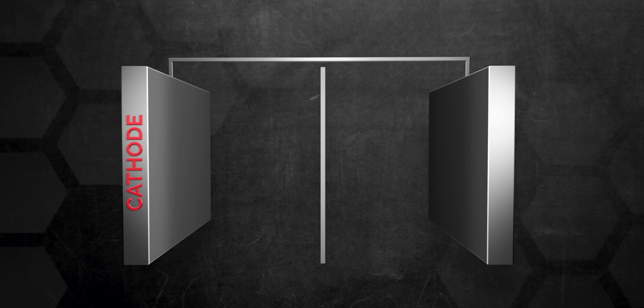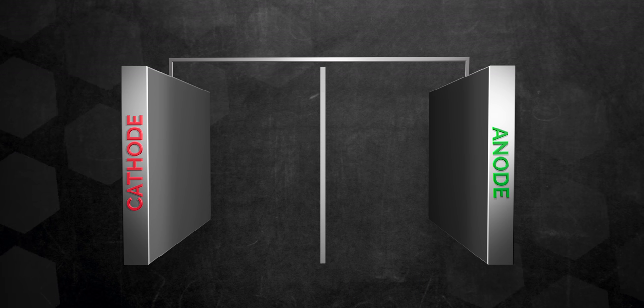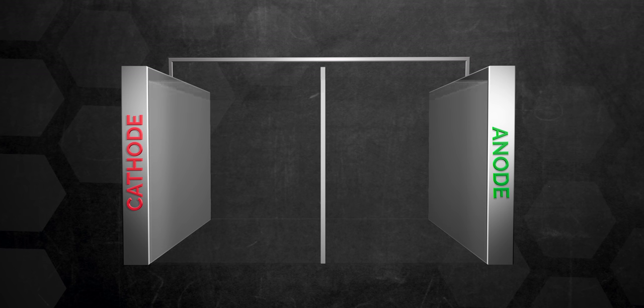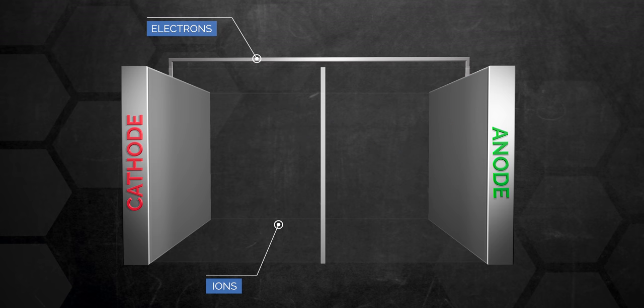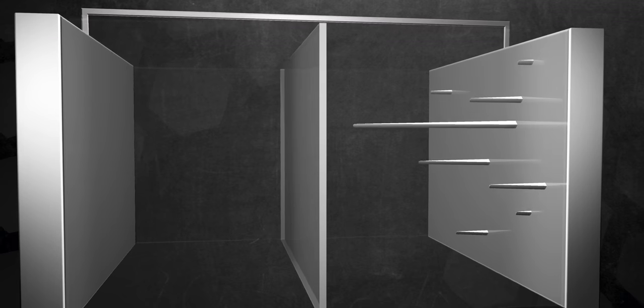There's a positive electrode or cathode, which is usually something like a nickel-cobalt-aluminum formula. Then there's a perforated separator to keep it isolated from the negative side or anode, which is usually a compound of a carbon material like graphite. Finally, all of this will be filled with a liquid electrolyte that allows the free flow of ions back and forth between the anode and cathode during charging and discharging. You can substitute many chemical formulations for the cathode and anode, but the liquid or gel electrolytes in most of the batteries that we use today are highly combustible. This can happen because of manufacturing defects or damage to the cell, but it's also a problem because of something called dendrites. Metal can build up in the anode and slowly create stalactite-like growths, and those can extend and puncture the separator between the anode and the cathode, and that's when you get exploding batteries.